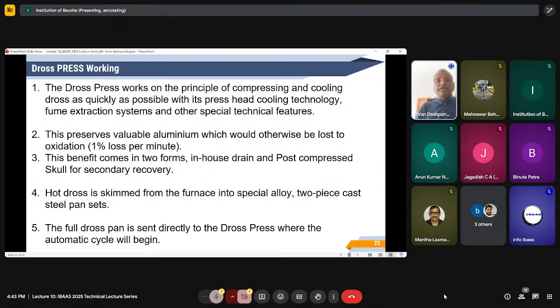This benefit comes in 2 forms. In-house draining, and after the compression, there is a post-compression skull. It has a large amount of aluminium trapped inside that skull, which you can easily recover. I have seen the best cast houses where they take the DROSS and spread it on the floor for allowing it to cool, but that is not the right practice because you are already oxidizing that, and because the DROSS is coming at 1000 degrees, a sizable amount of aluminium also gets evaporated. And if your de-drossing activity is manual, then your forklift operator will skim more of the aluminium rather than the DROSS. So these are the factors for which you can prevent loss by way of recovering the aluminium.